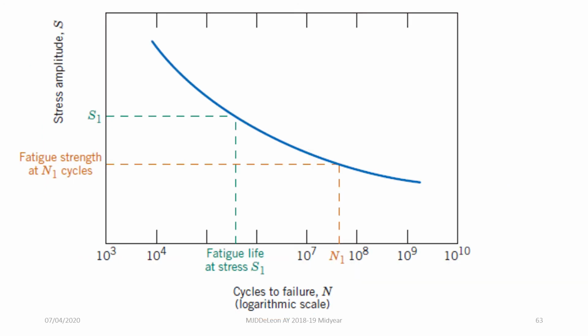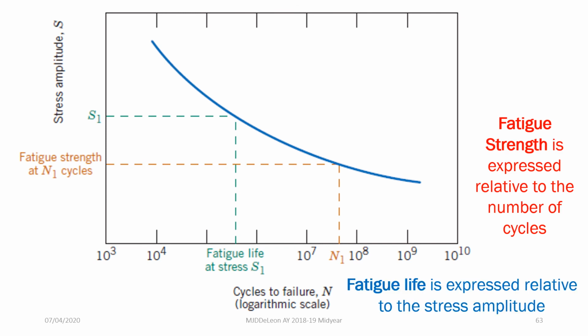So another type of SN curve is observed in alloys that are non-ferrous. So dito, wala tayong fatigue limit. So in this SN curve, we can extract two different data, yung ating fatigue strength and fatigue life. Yung fatigue strength natin, this is expressed relative to the number of cycles of your material. So, for example, we're looking for the fatigue strength at 10^7 cycles since we're expecting that in your material's lifetime, it would undergo 10^7 cycles of that repetitive stress. Makita natin that your fatigue strength at that one is at this level here.